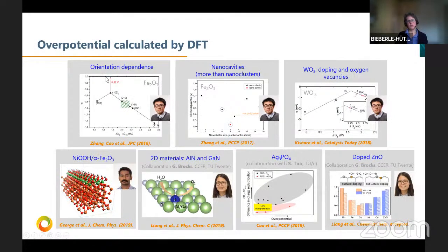And we looked at different systems, so iron oxide, tungsten oxide, but we also worked a bit with 2D materials, with lately a paper that was just accepted yesterday on doped zinc oxide. And we looked at the overpotential dependence on different materials, orientations, cavities, vacancies, and these things, in order to find out what is really determining the overpotential in these systems.